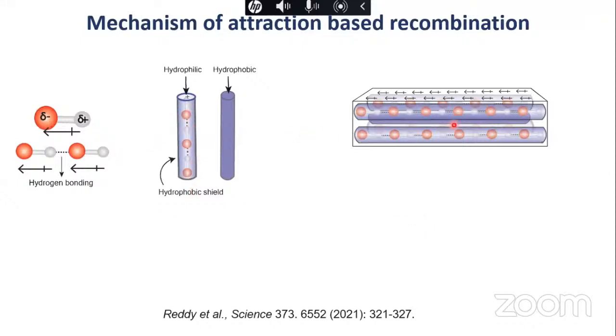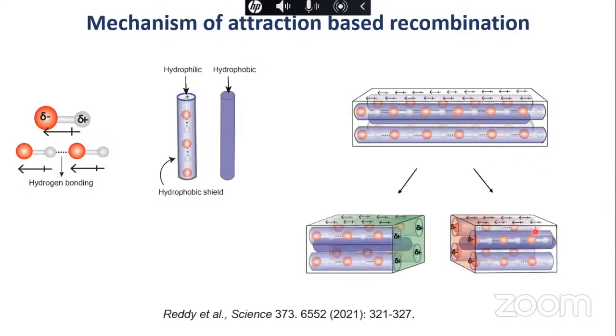For example, these crystals have hydrogen bonded chains in the crystal structure, and all of these have one particular orientation. All of them are in one direction, and because of that, your dipoles are aligned in one particular direction. When you break this crystal, on one side you have heads, and on the other side you have tails. So your dipoles are different, and since there is possibly a small plastic deformation or fatigue in the crystal, the charges don't go off completely. That is why there is a good amount of surface charge, which allows these crystals to combine and then self-heal completely.